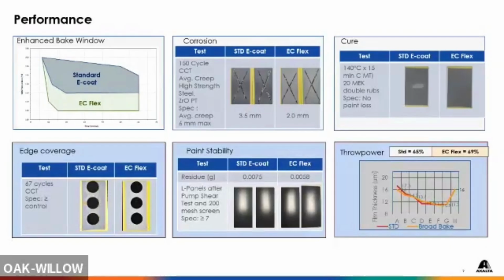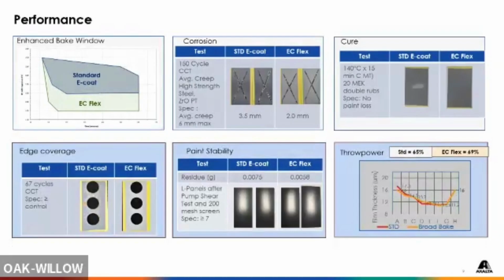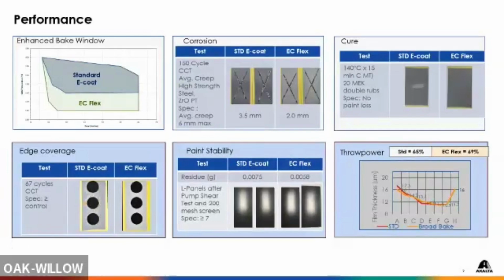I guess we overdid it on some of the submission work, and these were allowed to remain in the cabinet and continue to go. And then on the right, that just confirms the cure test. Very simple, rudimentary test. Basically, we take MEK or MIBK, and it's 20 double rubs, and the specification is no paint transferred to the white cloth, right? So as you can see at 140 C, our standard Ecoat is not cured. It has not cross-linked. It will not be a good barrier for corrosion, whereas the EC Flex does.